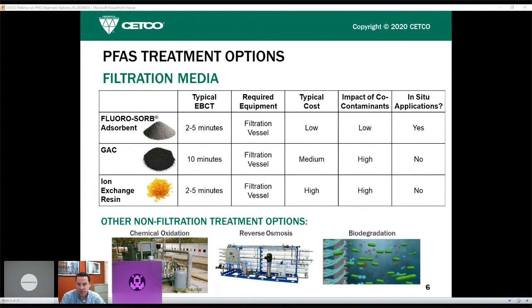If you look at the cost relative to other media, FLUORO-SORB is the lowest cost. And we have data, which I'll show you in a minute, to demonstrate that we are the most robust media to the impact of co-contaminants. And we can also be used for in situ applications like mixtures with cement. So I'll share that data at the end of my talk. So there are other treatment options. There's some newer things like chemical oxidation and even biodegradation, where you're actually trying to destroy the PFAS molecules. And another common technique is reverse osmosis. And that's typically used in things like wastewater treatment plants, where there may be other contaminants that you have to remove as well. Next slide, please.